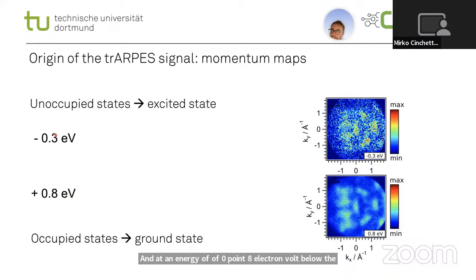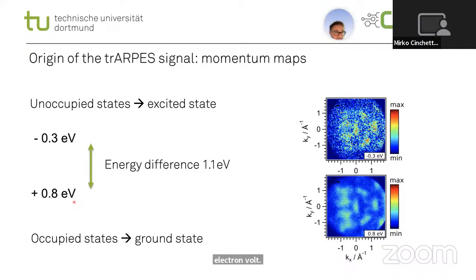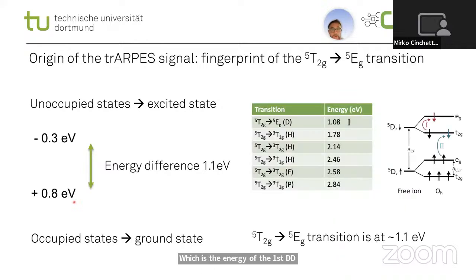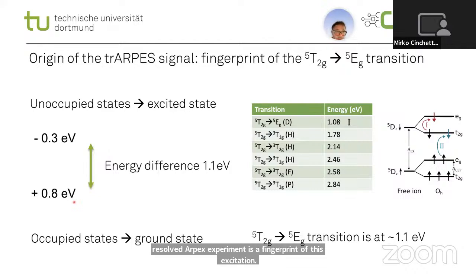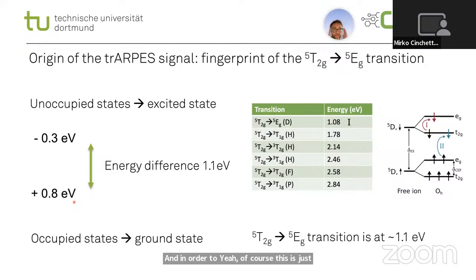So the energy difference between these two states is exactly 1.1 electron volt, which is the energy of the first DD transition. So we take this as a first hint that what we see in the time-resolved ARPES experiment is a fingerprint of this excitation. Of course, this is just a first hint. We need something more quantitative.